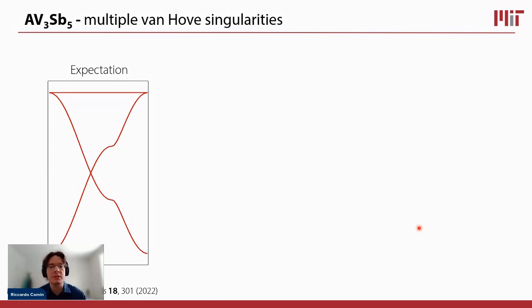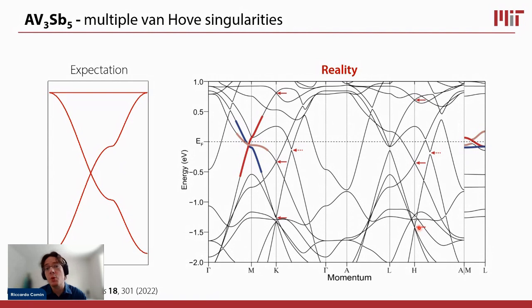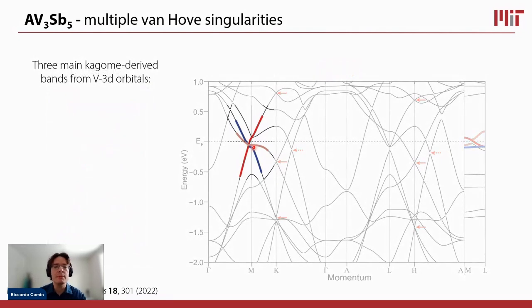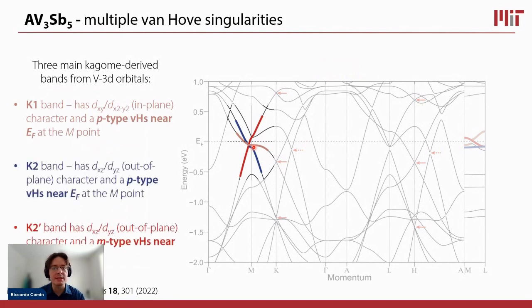So this is the simple expectation, based on a tight binding model, of what would happen on the Kagome lattice. Now, if we do DFT, density functional theory, to understand the electronic bands in the real system, by inputting the real structure of the system, then the reality comes out to be actually quite different. So this system has many electronic orbitals that are involved, and they form multiple bands. Those multiple bands tend to overlap, and so it's quite a jungle of different bands in the so-called spaghetti plot, which is what's shown here. But in particular, you will notice that there are 3 bands that seem to all have these Van Hove singularities, or these locally flat dispersions near the Fermi energy, near the chemical potential, which is where we expect that a pileup of density of states would drive the system unstable towards a broken symmetry phase. And so we see mainly 3 bands. I'll go quick through this, but we see bands that have different orbital character that form Van Hove singularities near the Fermi energy.